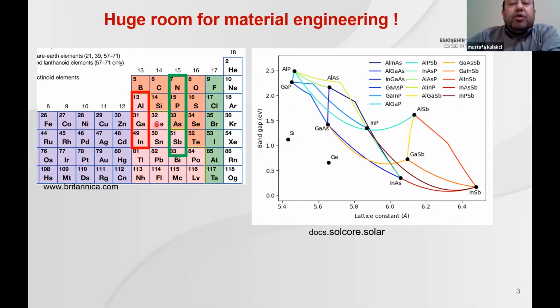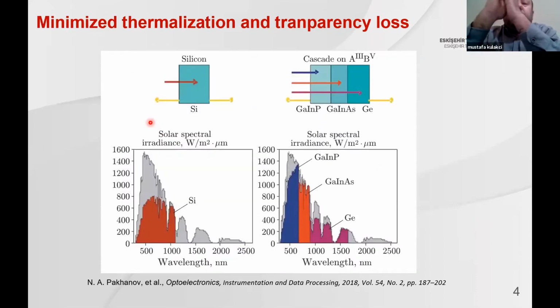Actually, silicon and germanium are also very important. Silicon is, you know, the workhorse of the electronic industry, and also the photovoltaic industry. Today, there is a huge amount of research combining silicon with III-V technology. Up to now, by either bonding or mechanical stacking techniques, very high efficiency solar cells have been produced, in either 2-junction or 3-junction, comparable with the matured III-V photovoltaics developed over germanium. The important thing is that you can tune the band gap of III-V compounds very easily, and you can cascade them in monolithic or non-monolithic structures onto a template or high quality wafers.